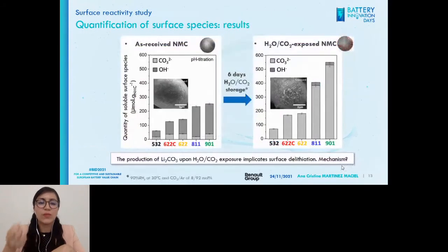With this protocol, we obtained several results. I will just show one of the most important ones. Here, you can see the results of acid-base titration of an as-received NMC surface, and also of a surface exposed to water and CO2 for 6 days.